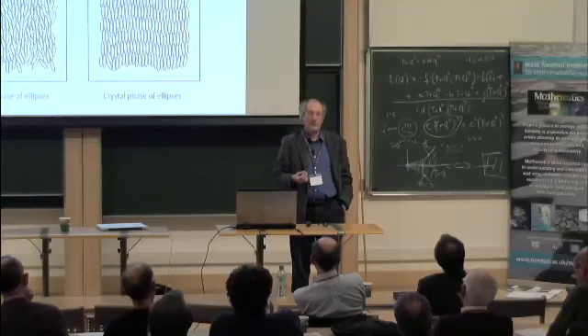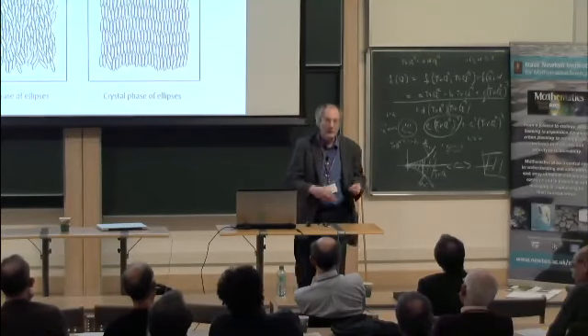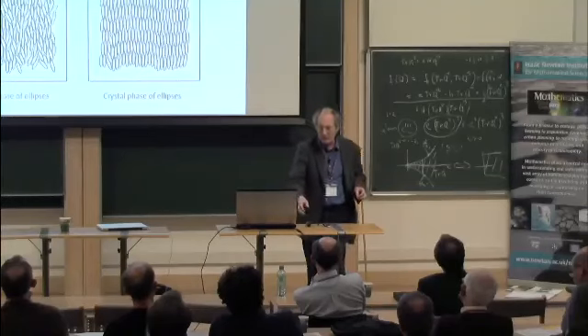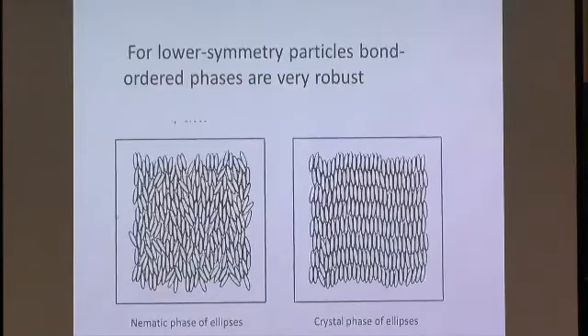But if the hexatic phase region is there, it's a very narrow density range only. Now, as soon as you go to non-spherical particles, like for instance these two-dimensional ellipses, it turns out that it is extremely easy to make bond order phases. So it actually becomes extremely hard to have real crystalline phases. So here you see a crystalline phase, and again, it's something that we looked at not in much detail, but if you look at these crystalline phases, it turns out that it's not so obvious that they're a crystal phase.